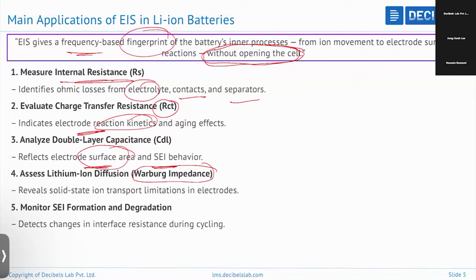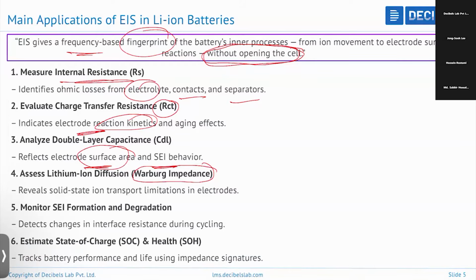Obviously, for LFP chemistry and NMC chemistry, or if you go to LTO chemistry or graphite chemistry, this Warburg impedance will be different because of the intercalation of lithium ions. Then it will also monitor the SEI formation and the SEI degradation upon usage of the battery. It detects the changes in the interface resistance during cycling. This technique is also used to estimate SOC and SOH. Of course, I have not covered this in detail in this seminar. In my course, I have explained it in detail. So overall, it tracks the battery performance and life using the impedance signature.